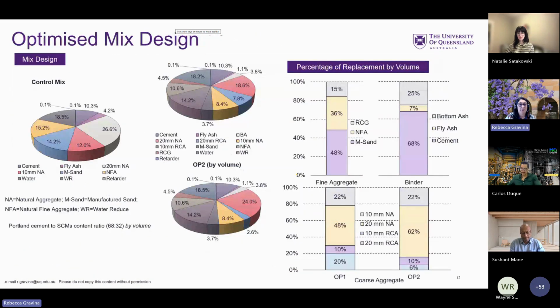In terms of optimized mix designs, we started with a control mix that satisfied the DOT's requirements for an N-class grade concrete with a minimum target strength of 40 MPa. And with a certain amount of general purpose cement and fly ash, man sand, natural coarse and fine aggregates, water reducers and retarders in the mix design. The Portland cement to SCM content ratio in the mix we adopted was 68 to 32% by volume.